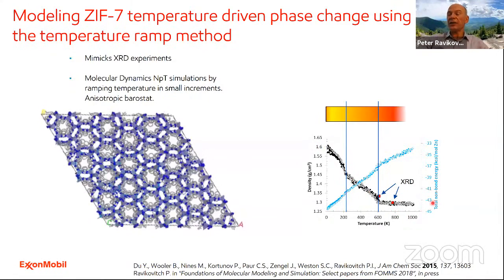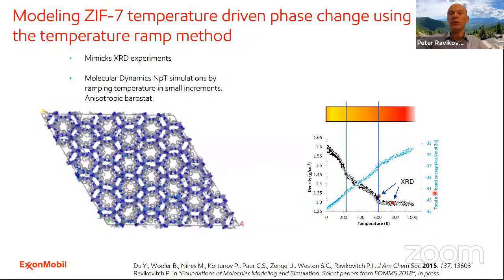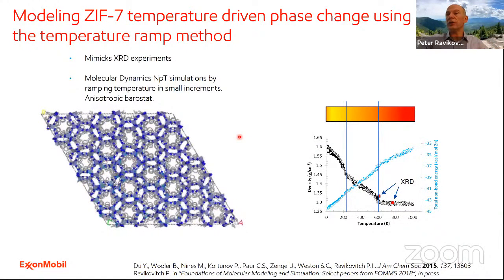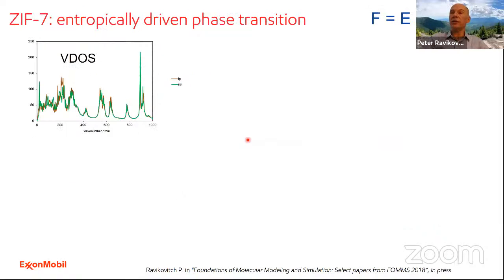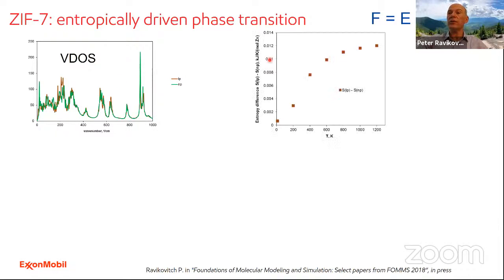So this is an example of an entropically driven phase transition, because in this case the entropy of the large pore phase is actually bigger than the entropy of the narrow pore phase. And we calculated these entropies using harmonic approximations. First, we calculated the vibrational density of states from molecular dynamics simulations for the narrow and large pore phases, and then we calculated the entropy difference. And indeed, the entropy difference for the large pore and narrow pore phase is positive.